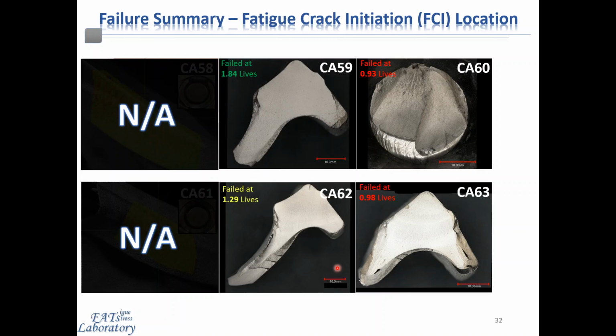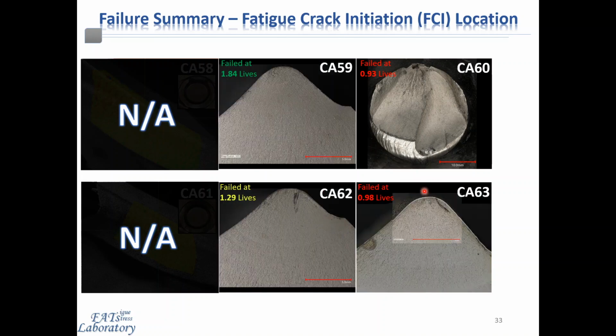Looking at the fracture surface of all of these components, we can observe a similar pattern for the three different failure modes. We can identify the location of the crack initiation to be the location of peak strain, which was accumulated in and highlighted in the DIC images indicated by the green crosshairs in the previous images. Now zooming in on these locations, we can see evidence of a forging defect called a fold line, where external flash fronts fold inwards upon each other to produce a cold weld or a cold shut of material, which results in poor fusion. So we can see that here, and some evidence of it here in these particular images.